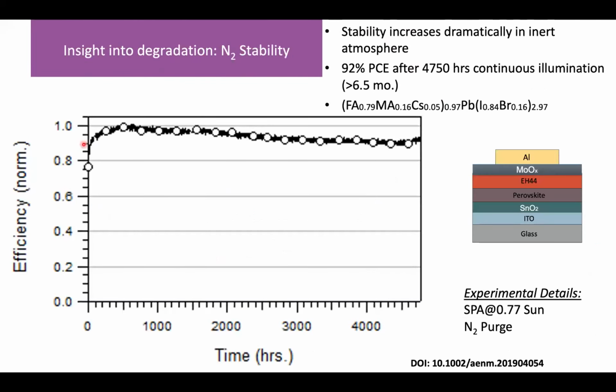And then this is some data that we've subsequently essentially validated for a little bit over 5,000 hours, so just under 5,000 hours. That's right, because it turns out making a 5,000 hour test is challenging because things like the lights go off. We'll lose electricity in thunderstorms and stuff, and that will impact some of these tests. But we made it 6.5 months, and we subsequently validated this data with follow-on studies where we were able to get to a full 5,000 hours and get very, very similar results in this particular device architecture.